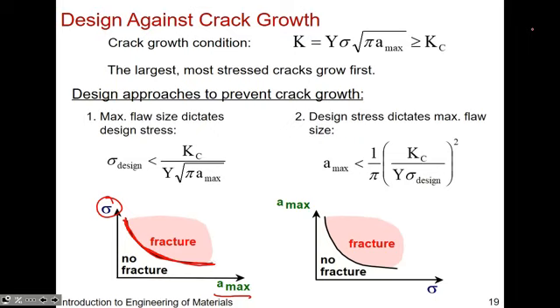There are statistics, though, as to where is safe really, because when you do these actual measurements, you have your specimen, that's a standardized size, all standardized dimensions. You do these torsional tests, you do the compressive and tension tests, applying stress where it will fracture, and you collect all this data. The error bar is actually something like this. So if you have an applied stress that's here and your crack length that began was, let's say, here, even if it's plus something and minus something for the crack length, it could fail. That is the cusp, okay?